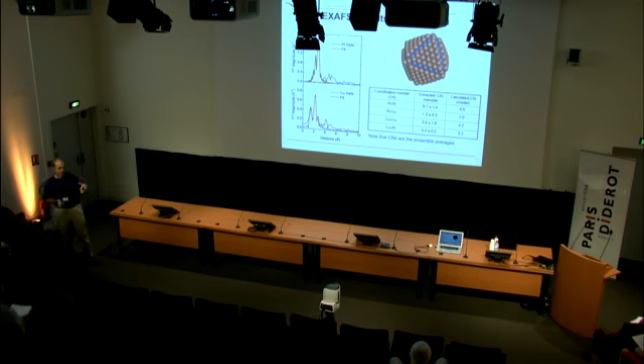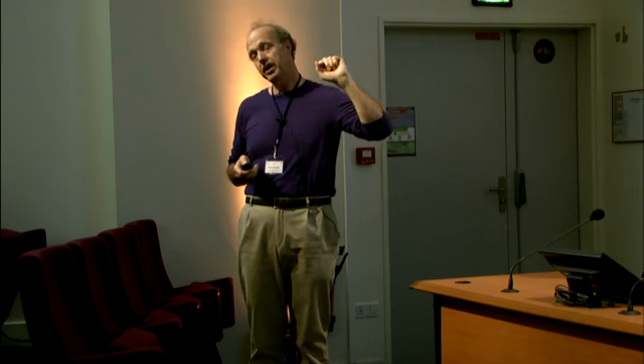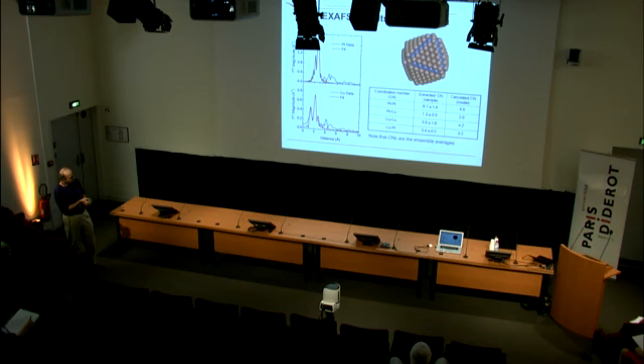So what I'm going to do is sum up, for every platinum atom, how many nearest neighbors this one has? And the range is 3 to 12. And I'm going to take the average, weighted by where all of the atoms are in the particle. And it turns out the calculated coordination number for this model is 9.5, and we measure 9.7. XAFS on particles like this is considered, this may look like a big number to you, but to XAFS people for materials like this, it's actually a very small uncertainty.